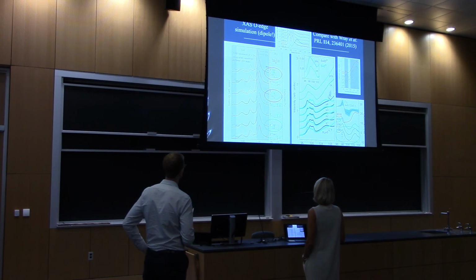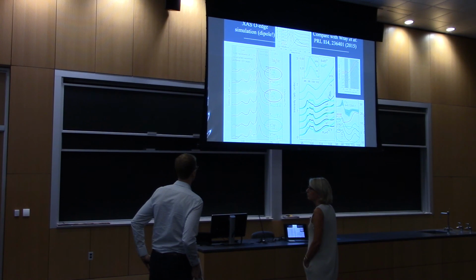You simply did the calculations here, the X-ray absorption calculation. If you do it for the gamma 5, you see this is the dichroism which you calculated for the X-ray absorption. This is what you observed. You have enlarged it. You have about something like 10.5%, you see. You calculate something like 40%, and therefore you are also corresponding to gamma 5 if I were you. But if you calculate the X-ray absorption, you clearly see more for the gamma 2, the gamma 1. So I think you can discuss that.